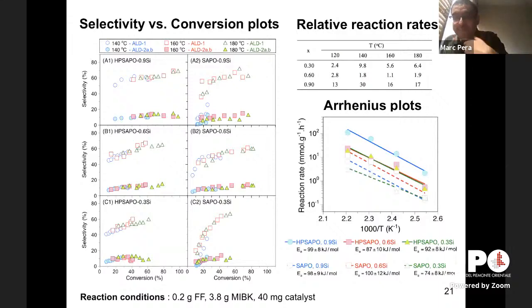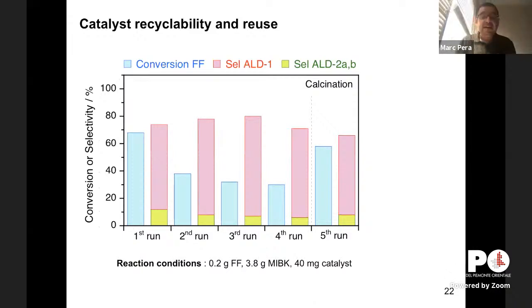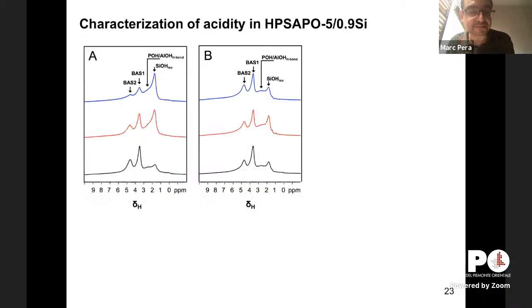We also measure all the apparent activation energies. The activation energies that we have are not very different. Even if the reaction rates are different, the apparent activation energies are not very different for different materials, more or less about 80, 90, 100 kilojoules per mole. So it's a reaction that requires some temperature to be operated. In terms of recyclability, we see that after the first cycle, we have some drop down, more or less stable, but by calcination, we can increase the activity, which points out that the main deactivation source of this catalyst comes from formation of heavy products blocking the access to the active sites.